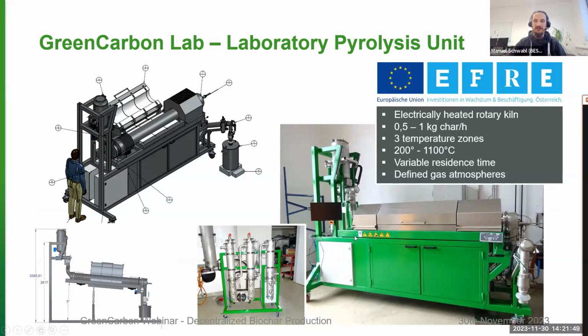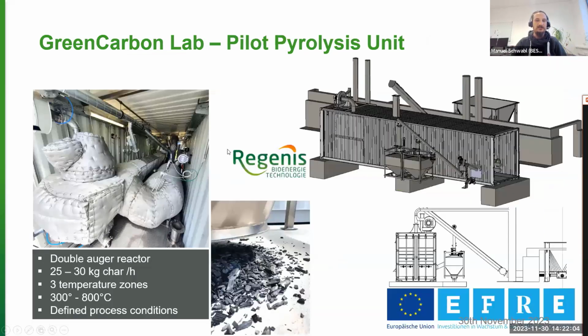You see the laboratory pyrolysis unit, small scale, 0.5 to 1 kilogram char per hour production, and up to 1,100 degrees centigrade within this rotary kiln. Then you see here the pilot pyrolysis unit, which is a double auger reactor with a production rate of about 25 to 30 kilograms of char per hour, reaching temperatures from 300 to 800 degrees C.